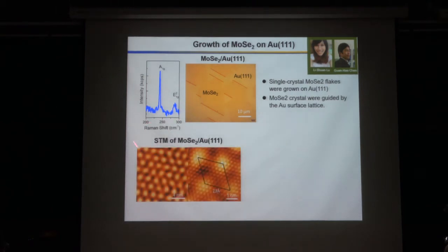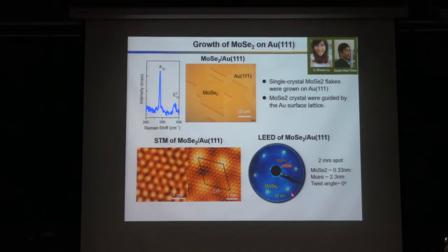And we also use STM to check. Similar to hexagonal boron nitride, they will form a Moiré pattern. And also, we use LEED patterns. You can see the MoSe2 crystal also shows very clear hexagonal spots, and also some Moiré pattern features in the LEED pattern. So it is clear evidence that the material is large area single crystal MoSe2.